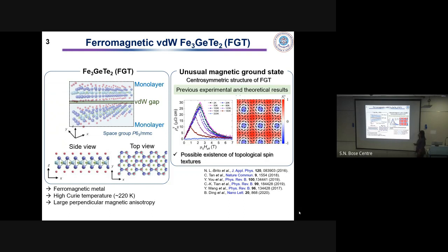So one of the key features, apart from this relatively high Curie temperature compared to other ferromagnetic systems, one of the most important features of this Fe3GeTe2 system is that it has a centrosymmetric crystal structure. However, from theoretical prediction, it has been shown that this system can possibly host topological spin textures. And also, there was one experimental evidence where people have observed an uncommon behavior in the magnetotransport data when they measured transverse Hall resistivity as a function of magnetic field. So this makes the system even more interesting.